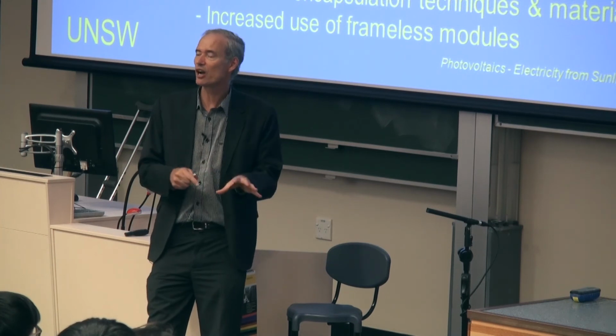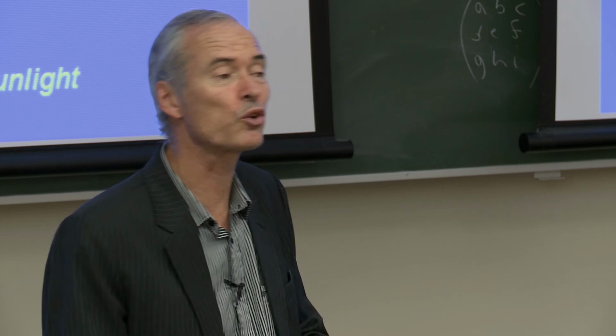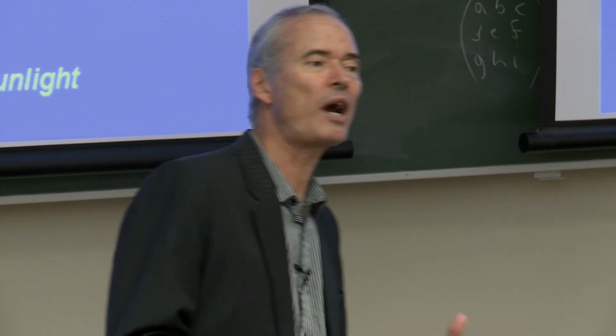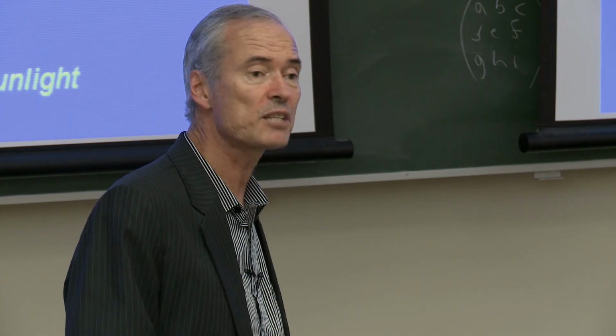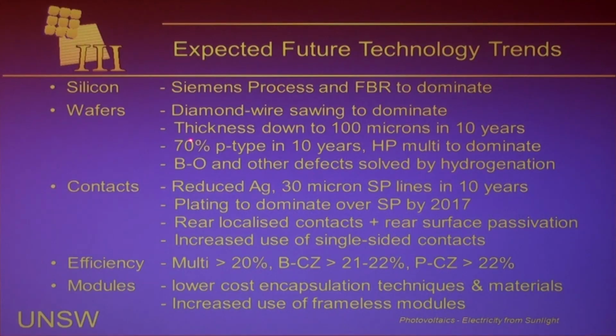So the challenge is thrown to the manufacturers to still be able to make their solar cells with the same yields when the wafers are substantially thinner. And that's where the challenge lies. So the expectation is that the thickness of wafers will decrease from the present around about 180 to 200 microns down to about half that, 100 microns, over the next 10 years. And that will also help bring down the cost.